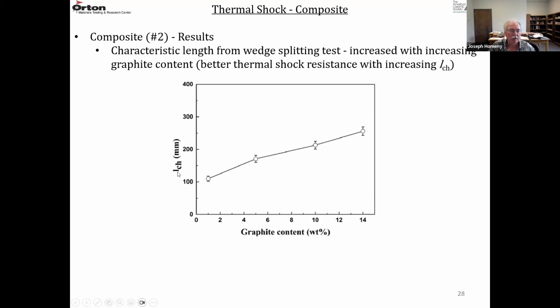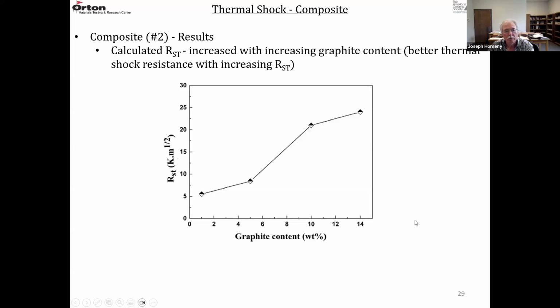They also plotted the characteristic length from the wedge splitting test. And again, that increased with the increase in the graphite content. So the higher the LCH, the higher the characteristic length, the better the thermal shock resistance. And that's following R4 prime. They also calculated RST, and they showed that RST increased with increasing graphite content. So the higher the value of RST, the better the thermal shock resistance. So all of these tests are showing that the material with the highest graphite content, 14%, should have better thermal shock resistance compared to the material that is only 1% graphite.